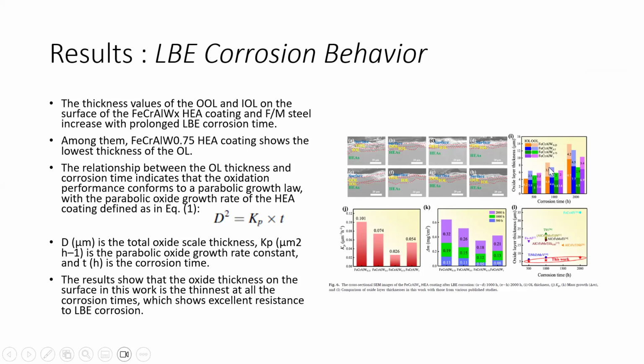Among them, the sample coating shows the lowest thickness of the oxide layer. The relationship between the oxide layer thickness and corrosion time indicates that the oxidation performance conforms to parabolic growth law, with the parabolic oxide growth rate of the coating defined in equation 1: d squared equals Kp times t. Here d is the total oxide scale thickness, Kp is the parabolic oxide growth rate constant in micrometer squared per hour, and t is the corrosion time. The result shows that the oxide thickness on the surface of this sample is the thinnest over the corrosion time. It shows excellent resistance to LBE corrosion.